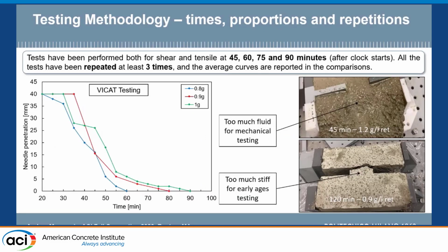We have also performed some Vicat tests in order to establish the right testing time according to these premixes. In particular, this is the testing time window we have selected, from 45 minutes to 90 minutes, testing every 15 minutes. We don't go after 90 minutes because the material otherwise is completely rock solid and out of the scope of this experimentation, and we didn't use retarders higher than 1 gram per liter, because otherwise the material is still too fluid even after 45 minutes.